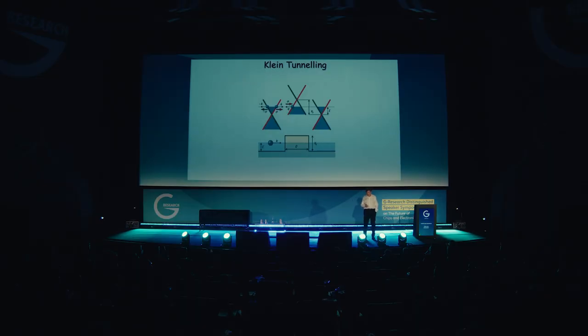And because Christoph asked me to do it more scientific, this is for people who studied quantum physics. On the left, particles are rejected by the barrier, and it goes through for the case of graphene. If you like to take it to another level, in terms of how we illustrate formulas in one of my papers from 15 years ago, essentially you have electron, and when it goes under the barrier, it matches everything: momentum, energy, speed of incoming electron. Or you can consider electron under the barrier converts into the positron, and then exiting the barrier, it converts back into electron. That's Klein tunneling. Electron doesn't notice this barrier because this conversion is essentially perfect. So the experiment has been done many times these days using graphene. And this is property which you have to take into account in any electronics or whatever you do with graphene. This essentially explains why graphene is so conductive. Because whatever impurities you put on the surface, they cannot stop electrons or apply gate to imply voltage or concentration there. They don't stop electrons from propagating. Both good in case of high transparency, high conductivity, but bad in terms of making transistors.